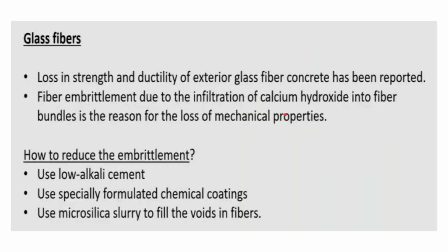The glass fibers result in loss in strength and ductility over time. It has been found that this is because of fiber embrittlement due to the infiltration of calcium hydroxide into fiber bundles, which results in loss of mechanical properties. This reduction in mechanical properties due to embrittlement can be decreased to a great extent by using low alkali cement, specially formulated chemical coatings, microsilica slurry for filling the voids in fibers, etc.